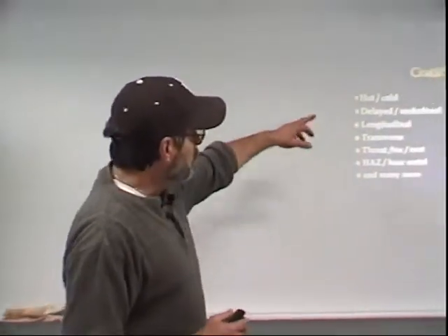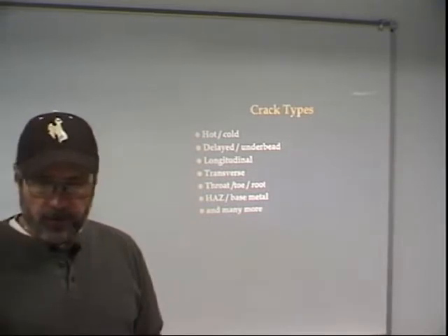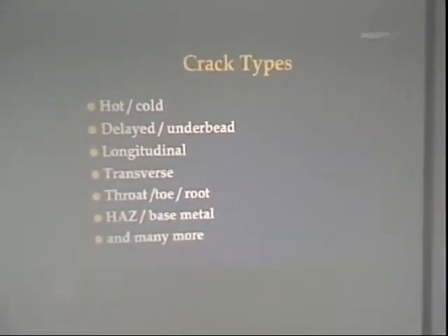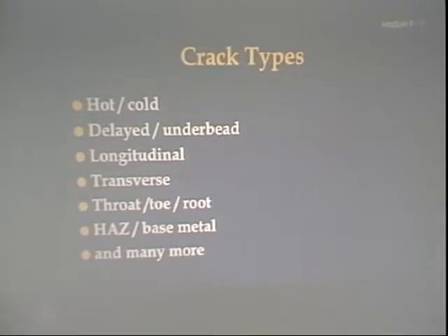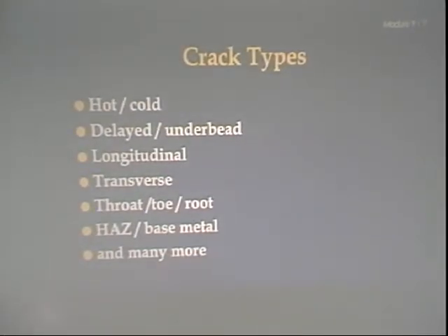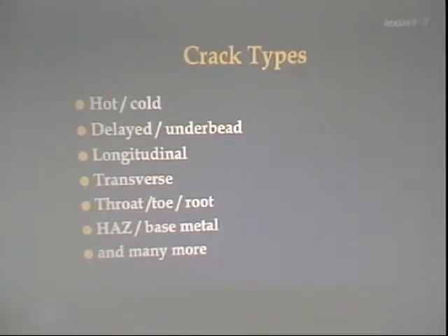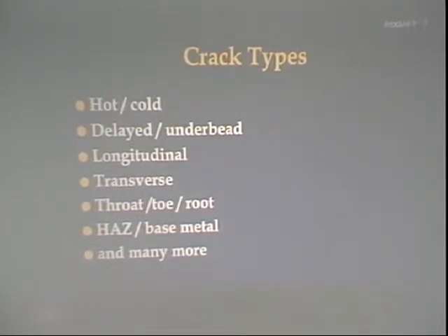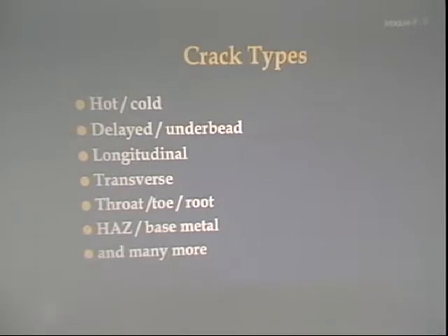And then in the middle of the second column, we're going to read about hot cracks. This is in the third paragraph, in italics. Put a bullet by it, underline it, highlight it. Usually hot cracks occur as the metal solidifies at some elevated temperature. The propagation of these cracks is considered to be intergranular. That is, the crack occurs between individual grains. If we observe the fracture surfaces of a hot crack, we may see various tempers, that is, colors on the fracture faces indicating the presence of that crack at elevated temperatures. I believe they also refer to those as chevrons. They're kind of like waves.